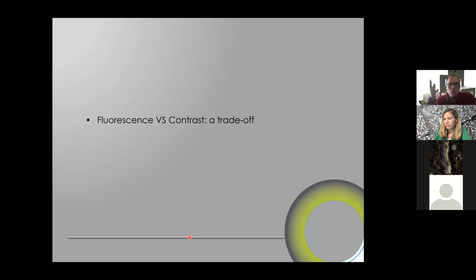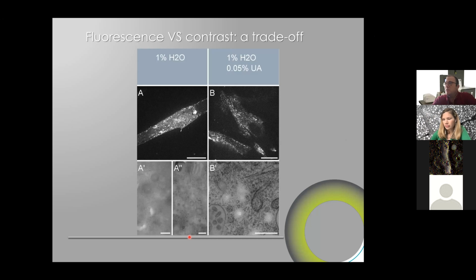Now, as I mentioned, when we put the uranyl acetate, whatever volume we put, this is a trade-off with the fluorescence. And already at 0.05% of uranyl acetate, we get some decrease in the fluorescence. That's something we noticed. But what is very interesting here is that in that case, I did the freeze substitution without any fixatives at all. And then here, this is the image of the sample after sectioning in TEM. And as you can see, the contrast is inexistent.